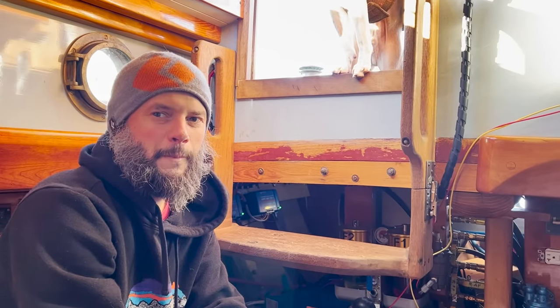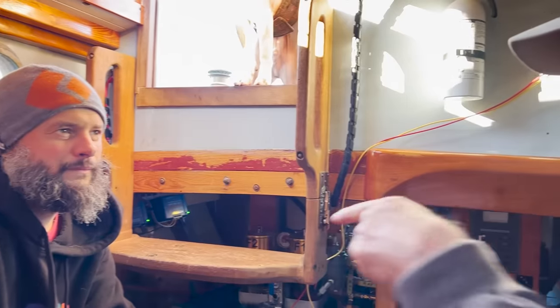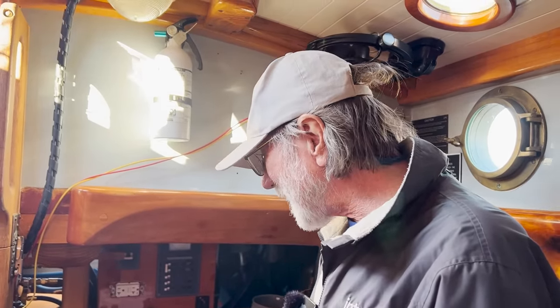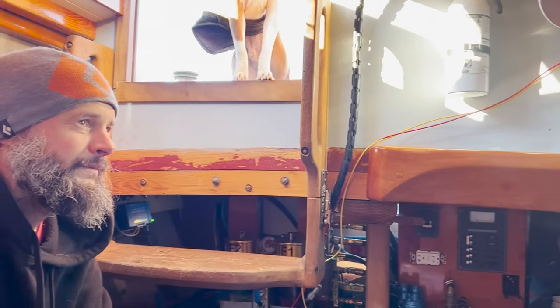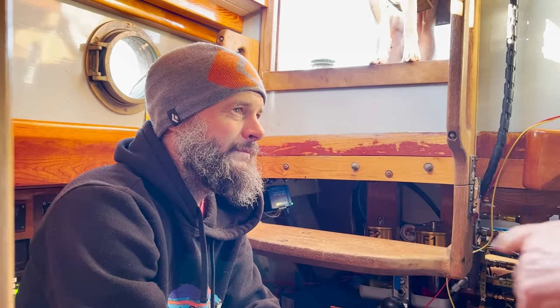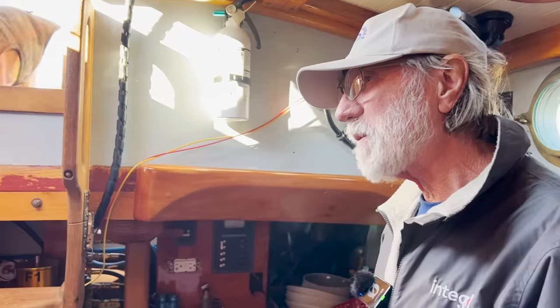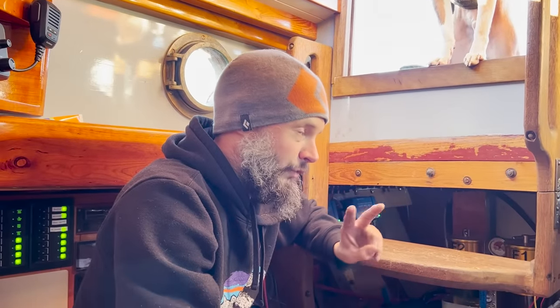And then when you said stray current, I was perplexed because I'm trying to think, how could we get a path that goes from positive out the zinc through the water and back to battery negative? Where are we going to get that path? For the life of me, I couldn't figure out a way of getting it. And I think the whole time we've been getting those fluctuating voltages is because when the engine's in gear and the shaft has been spinning, we've been measuring on the engine block, and probably we've been putting oil up into the gears, and we don't have such a good electrical path through the transmission anyway, back to the prop shaft. Okay. So by putting it on the stuffing box, we bypassed the transmission and the engine, and we went straight to there.